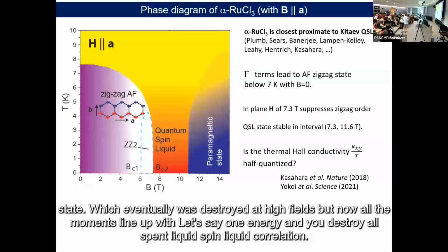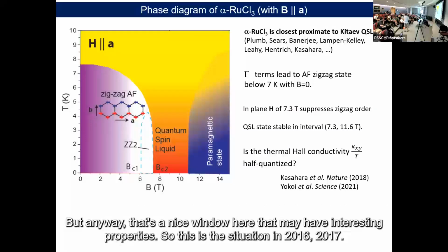And lots of experiments, especially neutron scattering, showed tantalizing evidence that this indeed was a highly disordered state, which eventually was destroyed at high fields, because now all the moments line up with the field by the Zeeman energy, and you destroy all spin-liquid correlation. But anyway, there's a nice window here that may have interesting properties. So this is the situation in